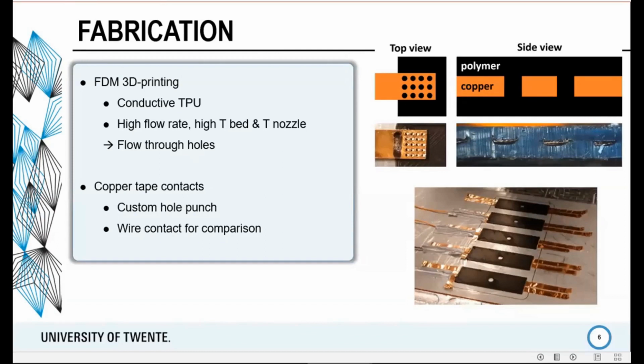And for the copper contacts, we've made a custom hole punch so that we can punch different patterns of holes to really try different designs. And we've also made wire samples. So we've made several samples with wires to compare to one of the most used methods, where people simply embed one wire into a print.